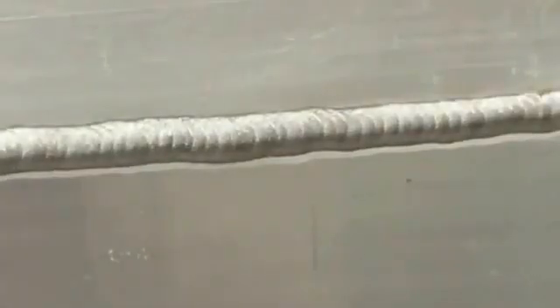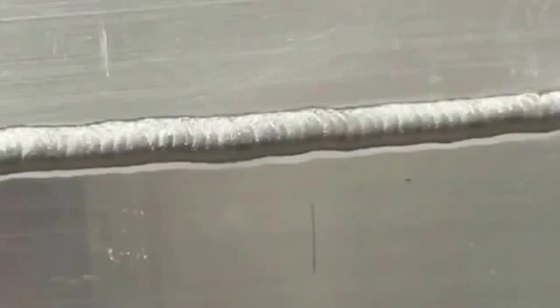Now just take a peek at the bottom toe of this weld. You will notice there is a slight band of cleaning action, a little gray or white looking area. The cleaning action, the cathodic etching from the alternating current, was breaking up the aluminum oxide there. There is none on the top toe of that weld. The argon was not reaching the top of the weld, and therefore the cleaning action was not reaching it. Cleaning action will only go where there's argon shielding. And so I needed a little bit more flow of argon just to shield that weld and weld area enough to get that cleaning action to work.